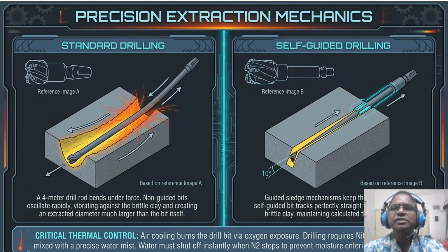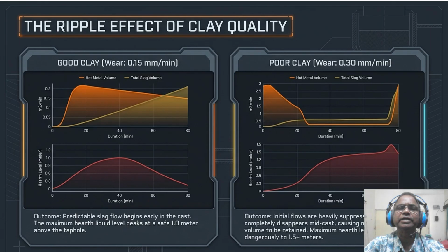So coming to our next slide, let's look at the data. On the left, a good clay has a wear rate of 0.15 mm per minute. The hot metal volume is stable and the slag begins early. Most importantly, the maximum hearth level peaks at a safe 1.0 meter. Now look at the poor clay with a 0.30 mm per minute wear. The initial flows are suppressed and slag flow disappears mid-cast because the hole is wearing too fast and losing suction. This causes hearth level to spike dangerously to 1.5 meters or more.